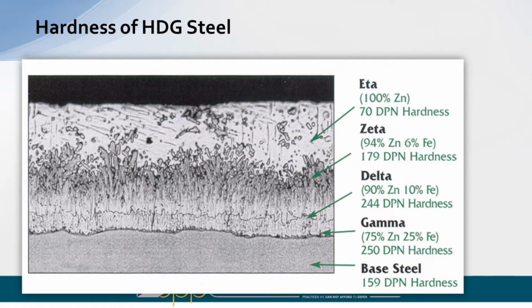This is another cross-section of a piece of steel. This is going to show the hardness that hot dip galvanizing gives you. Down here, you're going to see the base steel is at 159 on the diamond hardness scale. Your gamma layer here, though, is 250, delta 244, zeta 179. So these three layers here are actually harder than the base steel. And that's why it's very scratch resistant. It's not going to damage easily in the field. An iron worker is putting it up and he hits it with a file or a grinder even.